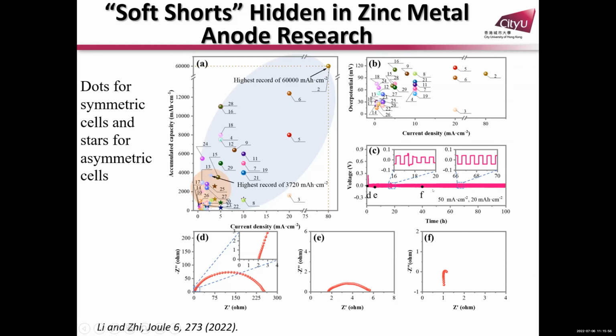And this is one battery. If you do a cycling test for a symmetrical battery, we usually do this kind of cycling test. If you only see the charge curves, it looks normal. But if you check the impedance, originally it's quite normal impedance. But at a certain point, for example point F, the impedance gets very small.